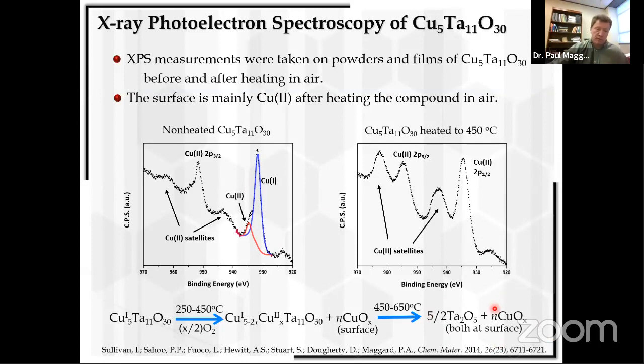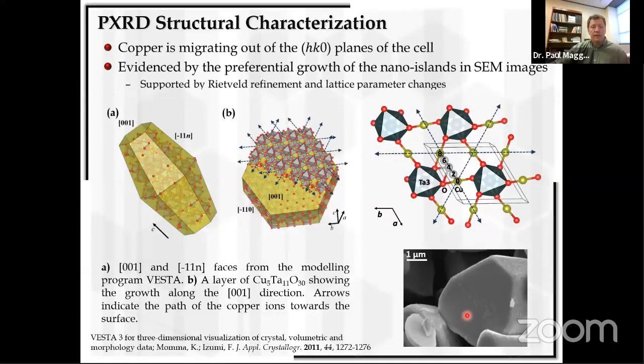Okay, and in this case, our photocurrents completely go away, right? And so the two temperatures I've shown you and their photocurrents, those were the highest ones that we could measure. Now we look at the crystalline structure, and we can say, yes, now we can understand how copper is coming out. Because if you take a look at the particle morphologies and how those pentagonal bipyramidal layers are oriented, within that network, between the pentagonal bipyramidal layers, you have the copper atoms, right? And they are located between the isolated TaO6 octahedron. And you can move them from one site to the next with a very low activation barrier.